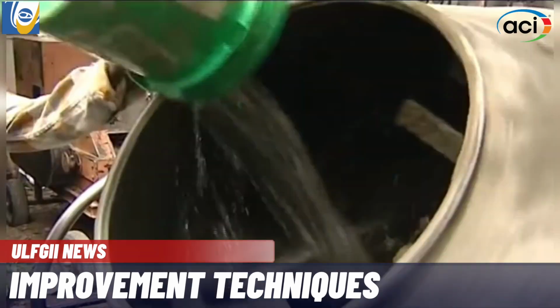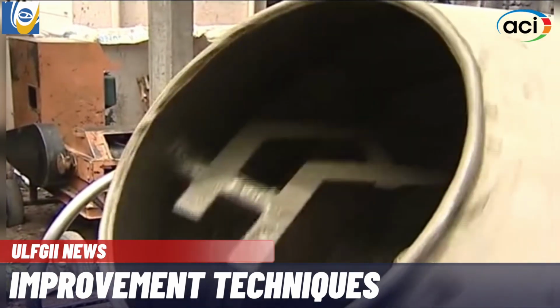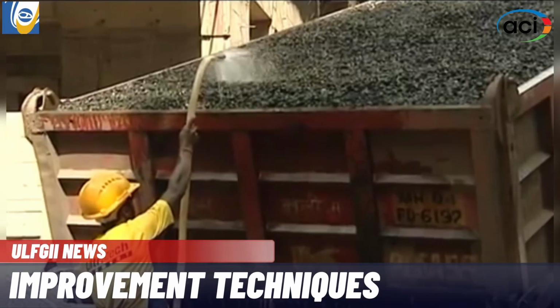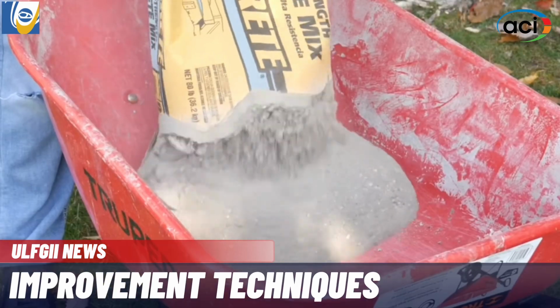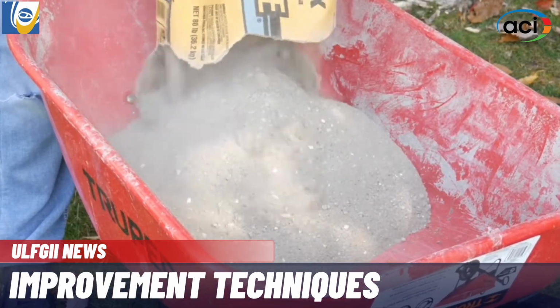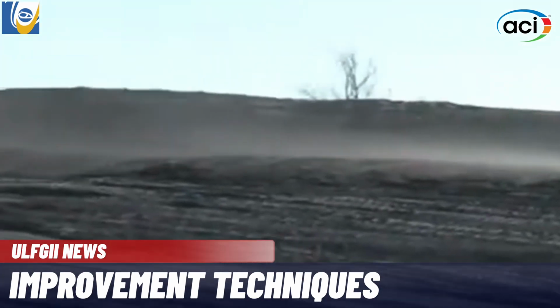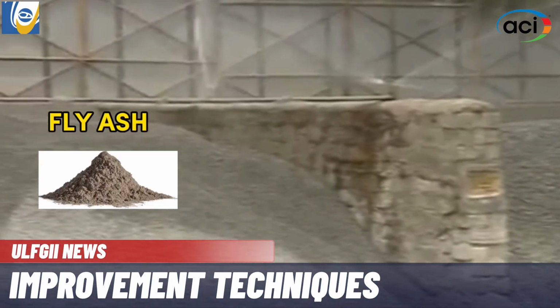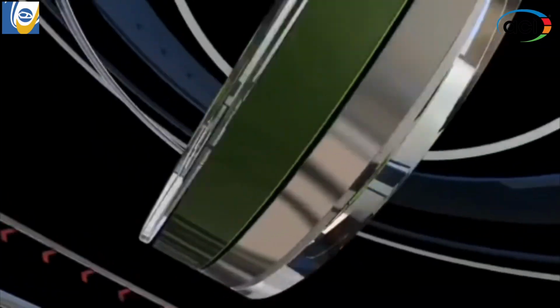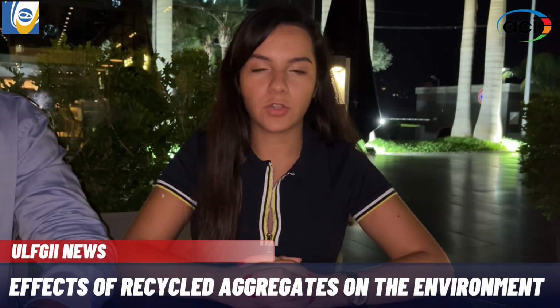We have improvements in mixing, like increasing the amount of water, pre-saturation of recycled aggregate in water, increasing cement content in the concrete composition, or the addition of minerals that will improve concrete properties like fly ash, blast furnace slag, and silica fume. Recycling the waste during the construction has a lot of advantages. Let's discuss its effect on the environment in this report.